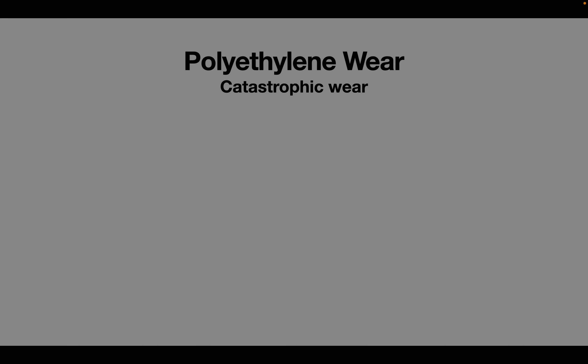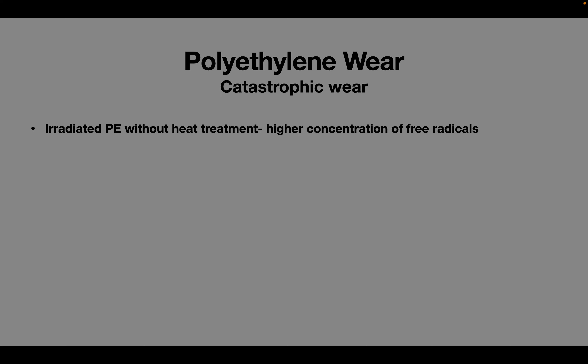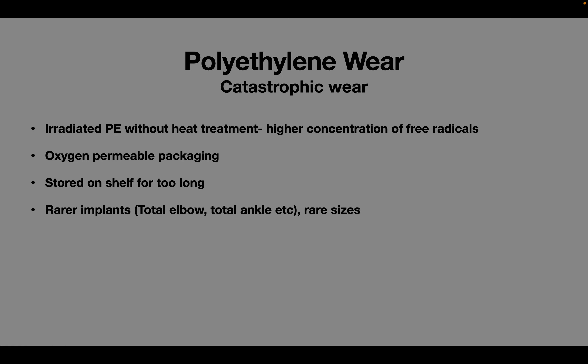We will briefly cover catastrophic wear of polyethylene in total knee replacement. Unlike polyethylene wear debris-induced osteolysis and failure in total hip replacement, catastrophic wear is a macroscopic failure of the insert. Relevant factors include polyethylene manufacturing, sterilization, and storage. If polyethylene is irradiated and not treated for removal of free radicals by melting or heat annealing, free radical accumulation occurs. If the package is permeable to oxygen and stored too long on the shelf — as in a rare-size insert — an atmosphere of chain scission is created, leading to macroscopic subsurface delamination and failure of the polyethylene. This is called catastrophic wear.